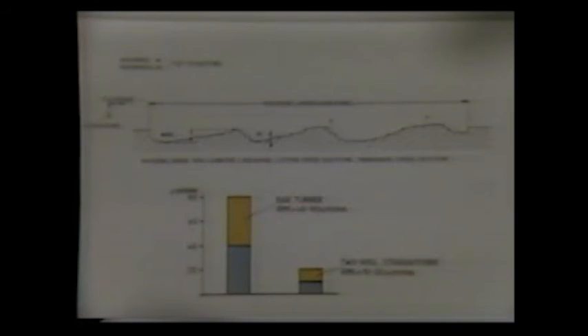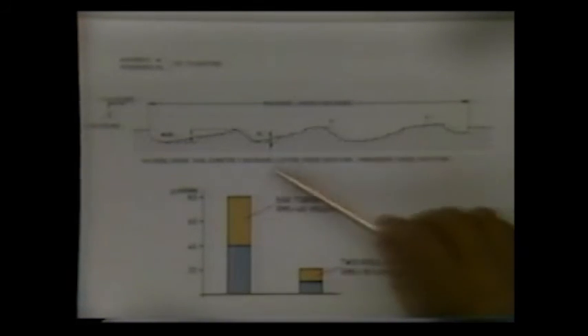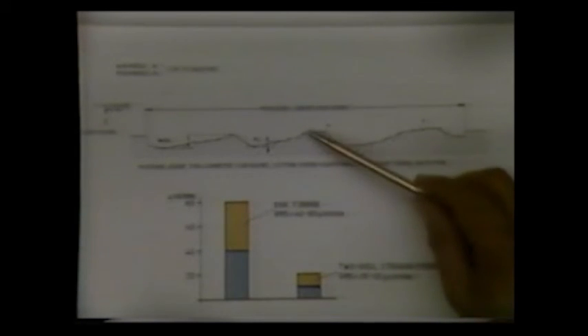As can be clearly seen, the surface is made up of two components: the waviness caused by the macrogeometry of the tool and the roughness caused by the microgeometry of the cutting edge. In the form which this waviness takes, the major cutting edges and side rakes are clearly distinguished, as is the advance of the material for each cutter head rotation. The average RMS values which can be obtained lie between approximately 14 and 80 microinches. You can see it here. The subsequent straightening or polishing process carried out in a two-roll straightening machine can reduce these values to nearly 10 to 20 microinches, as you can see here.